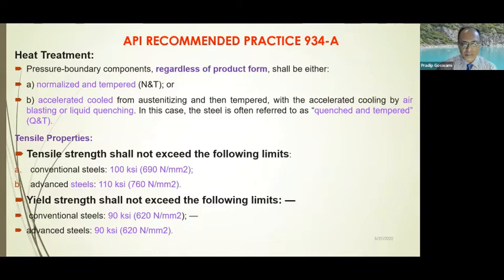And the tensile strength differs in line with the heat treatment process adopted. And as you see here, for the conventional steel, the typical tensile is about 100 KSI, and for advanced steel, it is 110 KSI. The yield strength at the same time is kept in the range of 90 KSI or so. That is definitely a property which is needed and which has to be watched out for at the procurement stage for the steels.